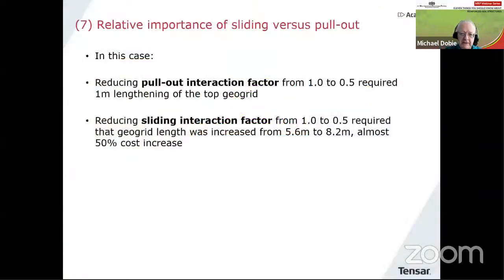So by way of summary, in the case I showed you, it won't always be identical every time you do it, but it'll be similar. So reducing the pull-out interaction factor from 1 to 0.5 required a 1 meter lengthening of the top geogrid. Whereas reducing the sliding interaction factor from 1 to 0.5 required that geogrid length was increased from 5.6 meters to 8.2, which is almost a 50% increase in cost of the geogrid reinforcement in that case. So it has a major effect.